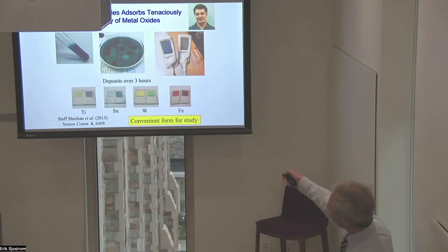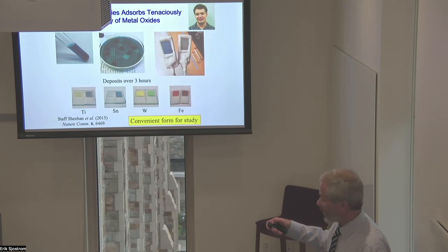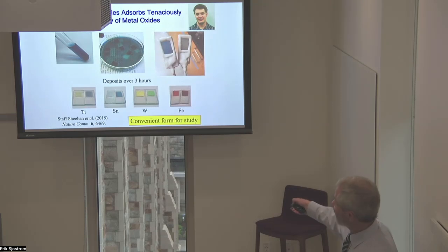But while he was with us, he showed that this blue solution species binds spontaneously and very tightly to a whole variety of metal oxides. And here are some examples: titanium oxide, tin oxide, tungsten oxide, iron oxide. Here's the blue solution. We made that using this catalyst activation step I mentioned. It's a stable blue solution. We just soak a film, a mesoporous film of these metal oxides, and it binds to the surface.